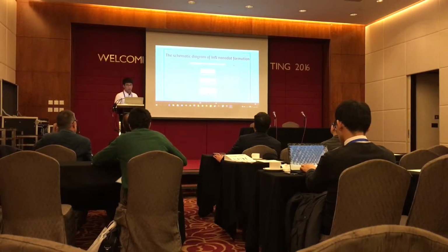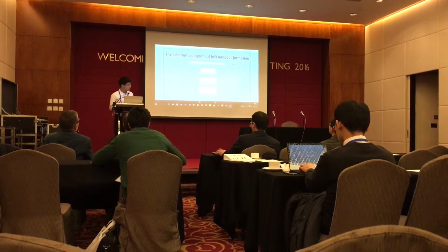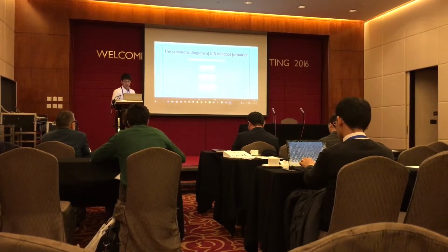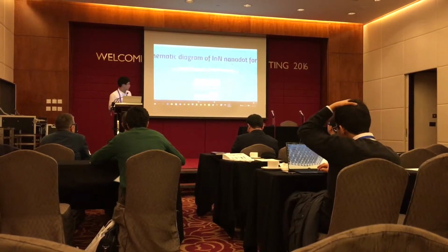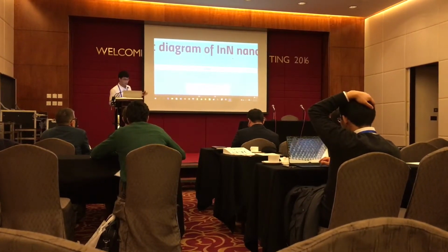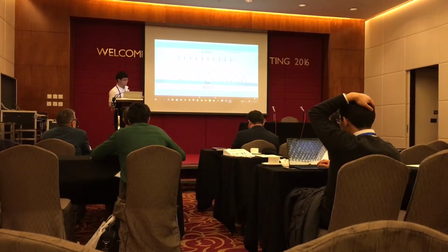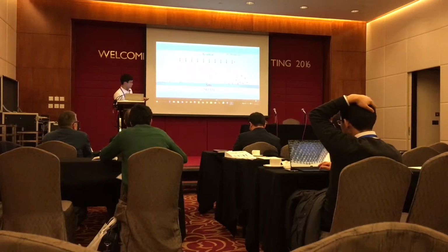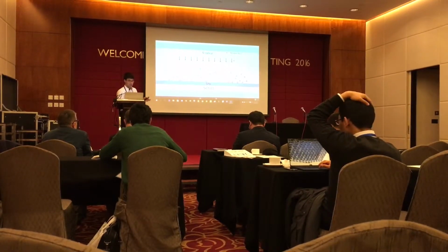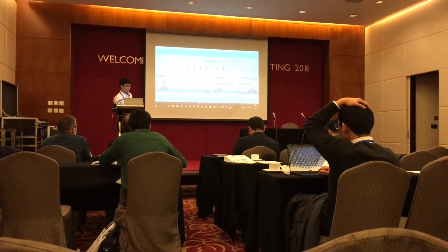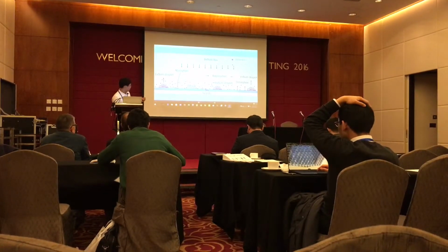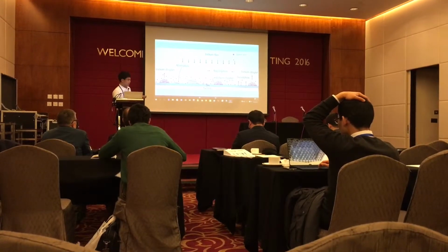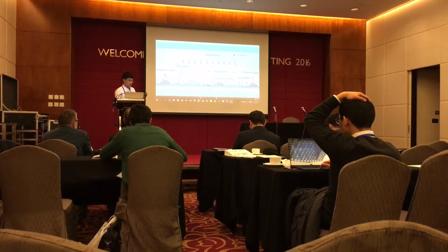So according to the analytic data we mentioned above, we graph the schematic diagram of indium nitride nanodot formation. After thermal cleaning, we do the pre-nitridation process, so a very thin silicon nitride film deposits over the substrate. Then indium droplet formation via adsorption, surface diffusion, and nucleation among indium atoms.